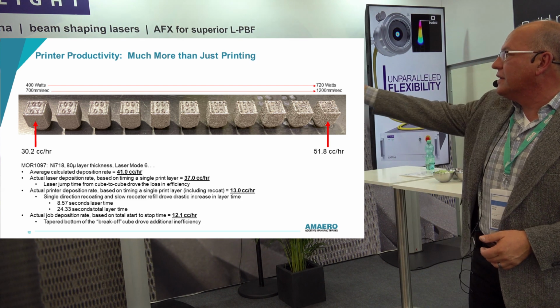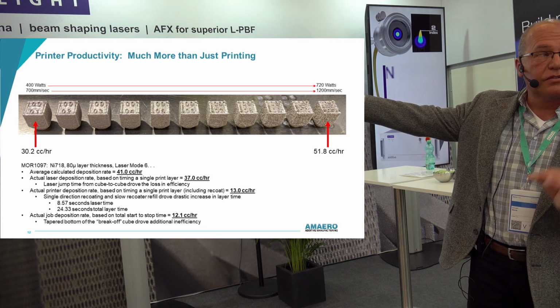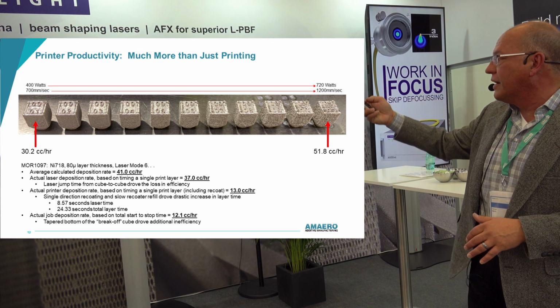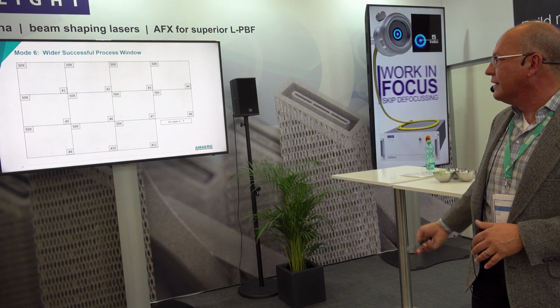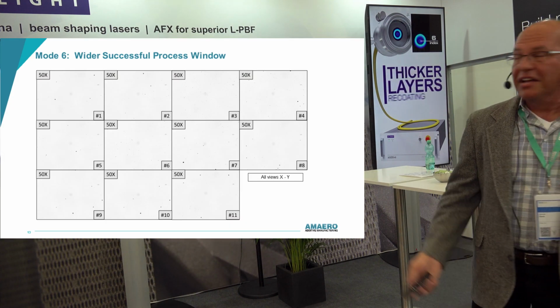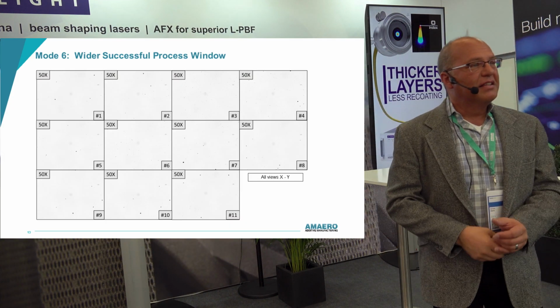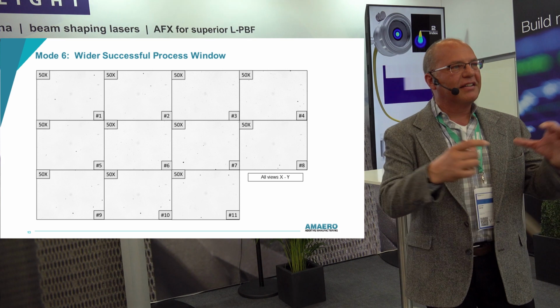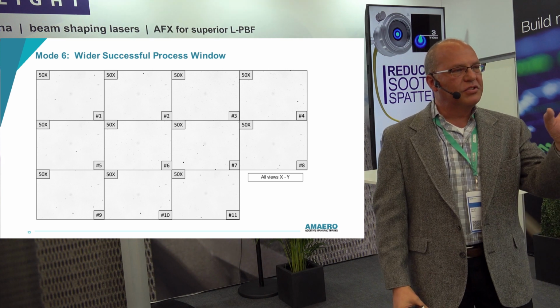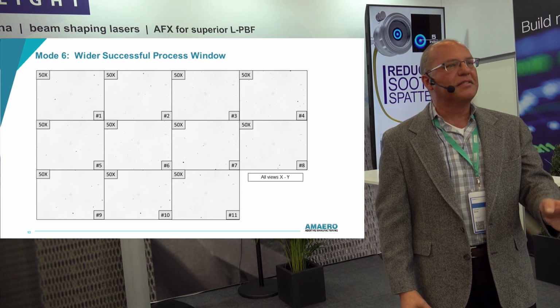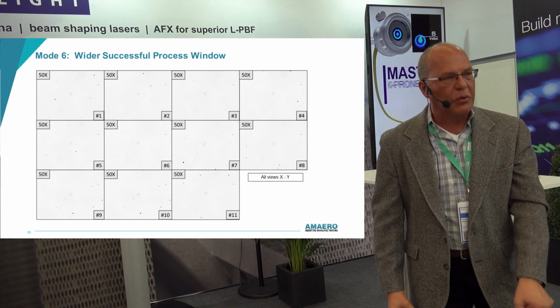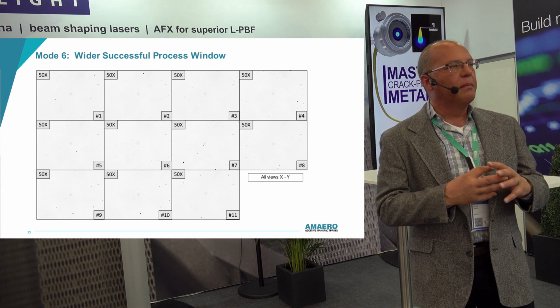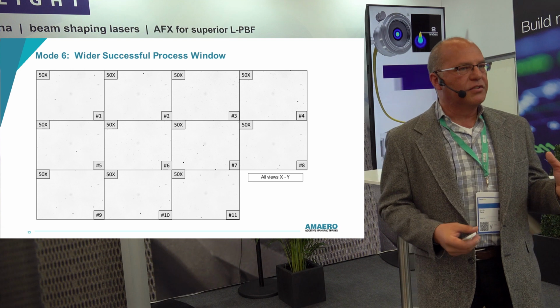And by the way, you would think that the cube on the left has great microstructure and the cube on the right probably has a bunch of porosity in it. Actually, no. They all look fantastic because of this gentle ring, hot on the outside, cold in the middle, a nice gentle ring that takes away that Gaussian spot, that takes away that deep keyhole effect, and gives us a much broader processing range from our materials.